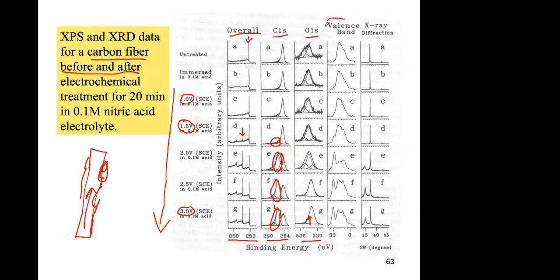The other part that is very interesting on this is the valence band that is close to zero binding energy, remember? And this gives you more information on the valence band. This is basically the external bands of the carbon. And you can see how it changes when you form the oxides. It has more structure. And this can be modeled as a density of states with the different external levels of the molecules that you're forming. So here you can see very defined peaks that may be defined levels in your system, probably highest occupied molecular orbital or other levels in your system.